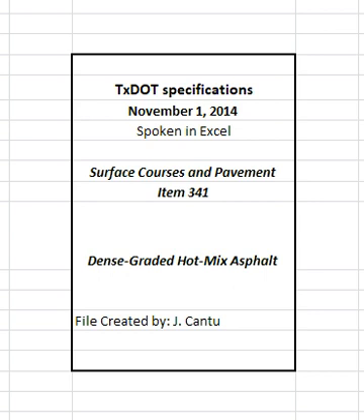Use of substitute PG binders may only be allowed at the discretion of the engineer if the Hamburg wheel test results are between 10.0 mm and 12.5 mm. Table 5. Allowable substitute PG binders and maximum recycled binder ratios. See table in specifications. 1. Combined recycled binder from RAP and RAS. 2. Use no more than 20% recycled binder when using this originally specified PG binder.